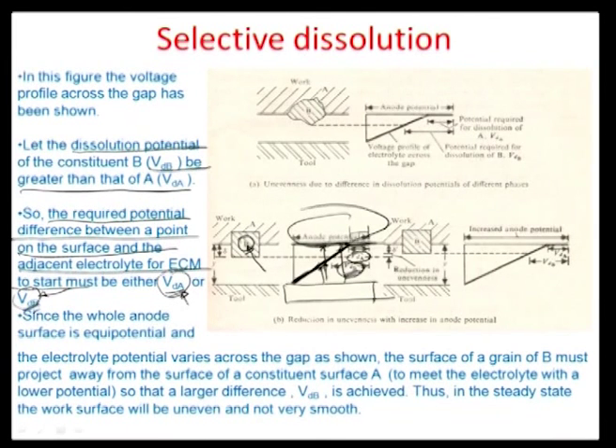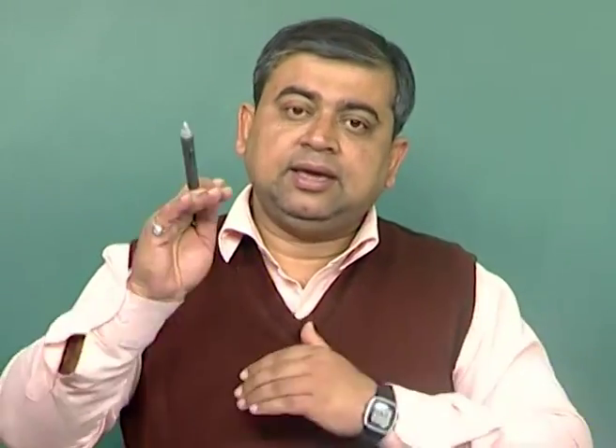or the workpiece surface. So VDB will only get dissolved when the part B is projected outside and it is meeting this potential line or potential plane here, which will give the potential VDB, right? So it is an auto roughening process. So B doesn't get dissolved beyond this delta dash value, okay? And A starts dissolving whenever it reaches, even if it reaches the anode, it starts dissolving. So if there is a close grain of B and A kept in unison, as almost always happens in alloyed states, A would dissolve more towards the surface, and B will only start dissolving when it reaches that potential front, okay? So there is a selective dissolution of A with respect to B, unless and until B ensures that it projects into the solution at the potential front, where available VDB would be able to dissolve away the B.